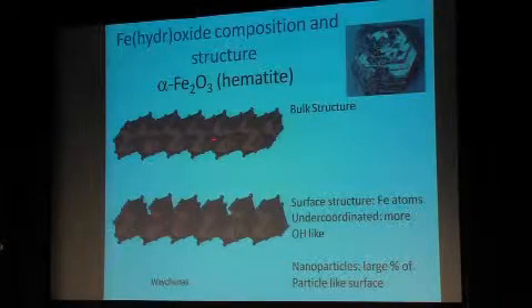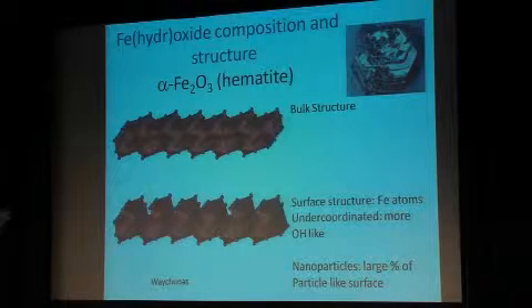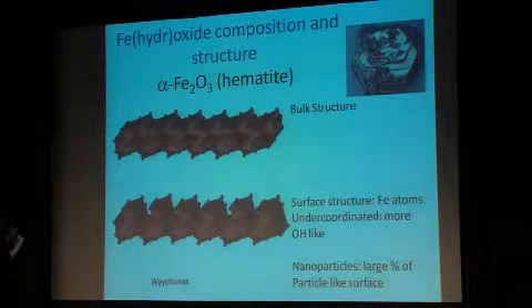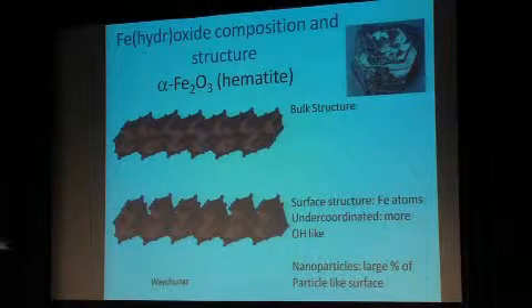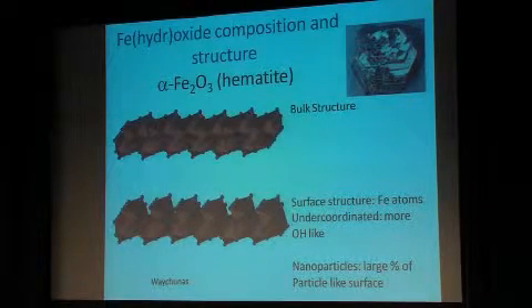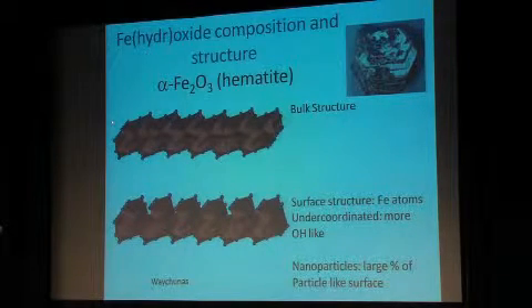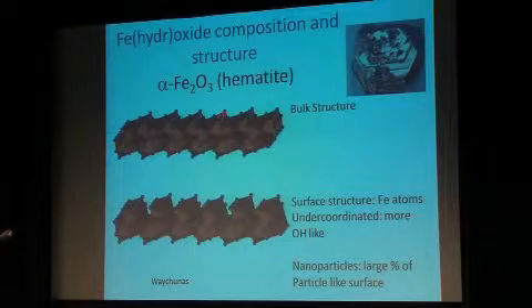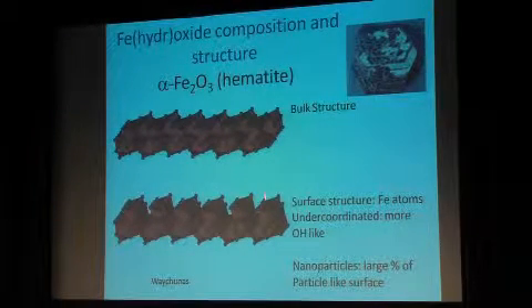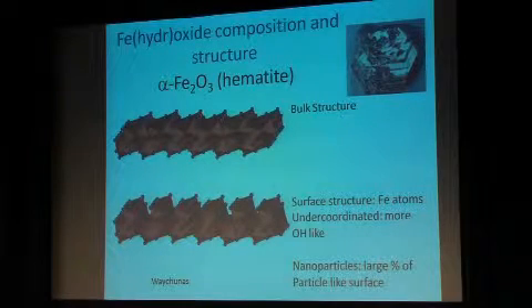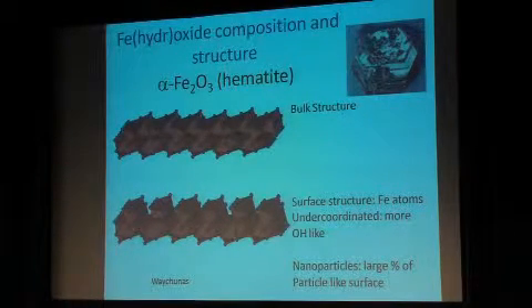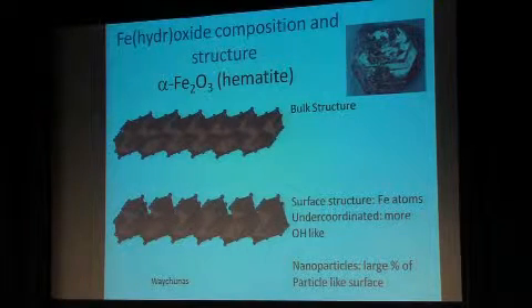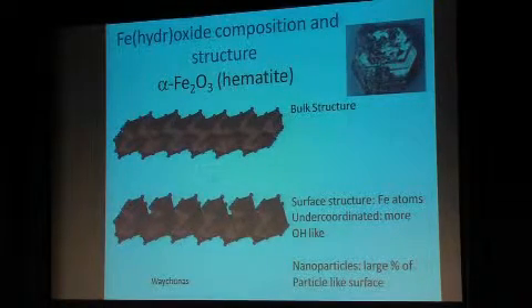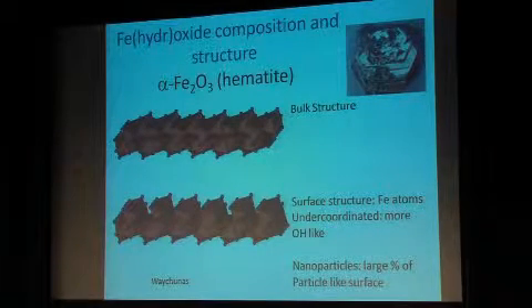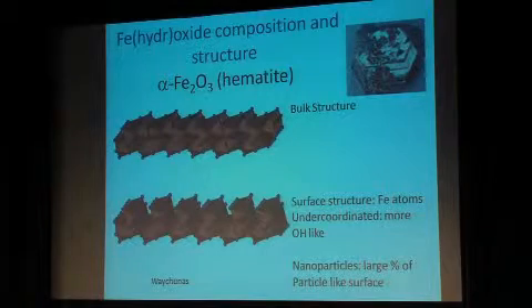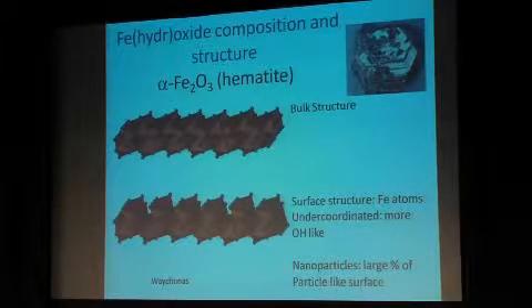The bulk structure in this model is really iron atoms surrounded by oxygen, and he's kind of done a model that I have a hard time looking at, except as a geologist. So here's what the surface structure looks like if you just were looking at the bulk structure. These really relate to irons with oxygens on them. At the surface of hematite, kind of every other iron atom is missing. It's not there. So what that means is that you've got a totally different coordination environment from if you've got the bulk hematite. And in fact, hematite takes on a more iron hydroxide rather than iron oxide structure at its surface.